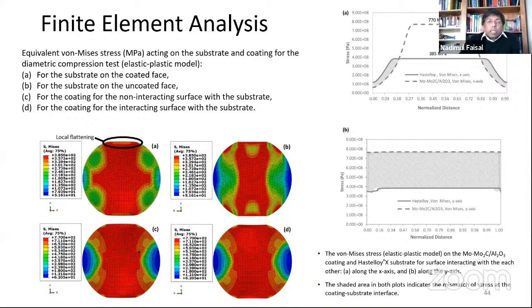Then we did some stress analysis using finite element. You can see there's a huge mismatch in the substrate and coating side. So if you want to compare these two, this is on the coating side and the substrate side and so on. So you will find that once you compress the coating surface and the substrate surface and the interface on the coating side and the substrate side, they would have different strain or stress distribution. So these would have an impact on the overall quality of the coating. So we think that this can be an alternative way to measure adhesive strength in thermally sprayed coatings.